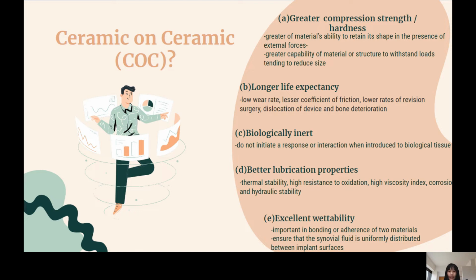To conclude, clinical results have confirmed a higher survivorship, lesser wear, and lower osteolysis, making these bearings an excellent choice for young and active individuals. Research also shows that ceramic on ceramic bearings decrease wear, bone, and muscle loss, and lower the risk of dislocation. The human body also tolerates the ceramic well with low reactivity and no toxicity.